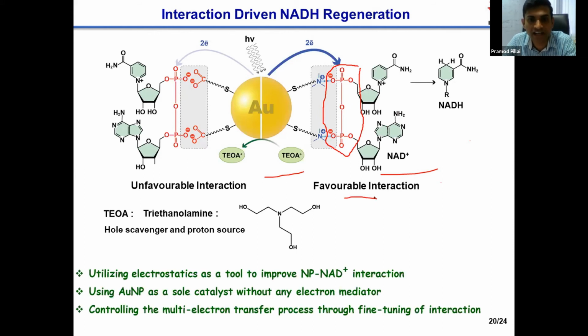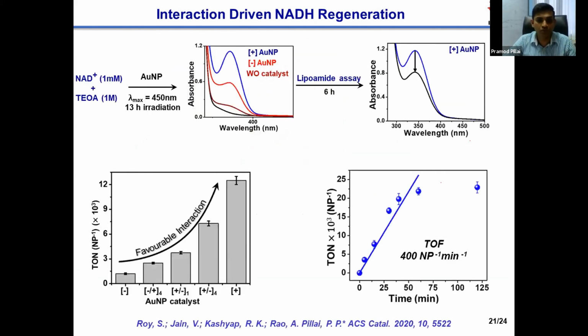So this was our idea, and this is a summary of our result. So as we increase the favorable interaction, we were able to see appreciable catalysis with only gold nanoparticles. So here you don't have any co-catalyst, any sensitizer. It's a sole photocatalysis with gold nanoparticles. So this is the power of surface chemistry. So what we have achieved here is a turnover frequency of 400 per nanoparticle per minute, which is one of the best reported values with plasmonic materials.